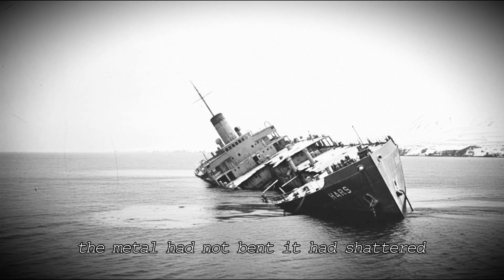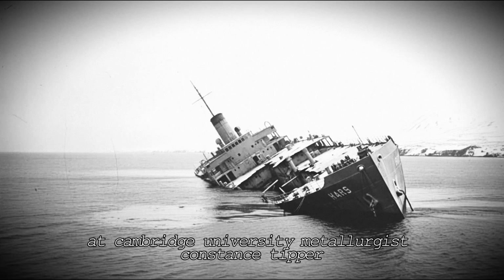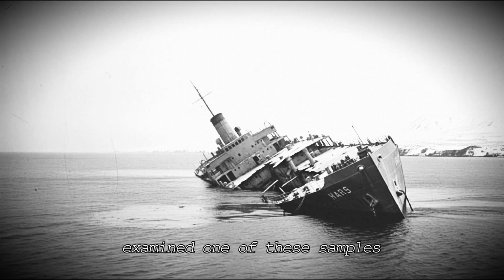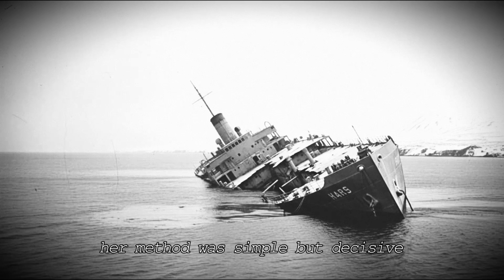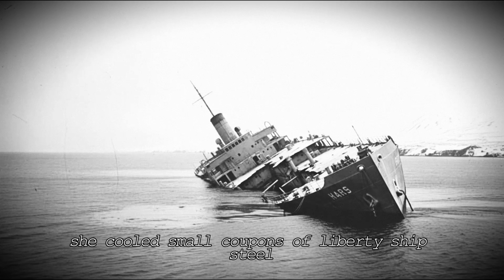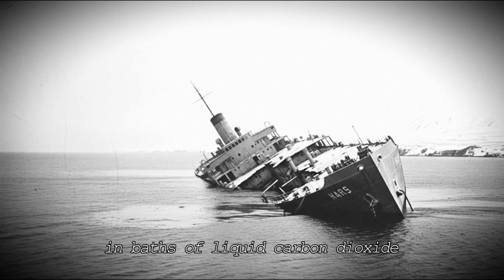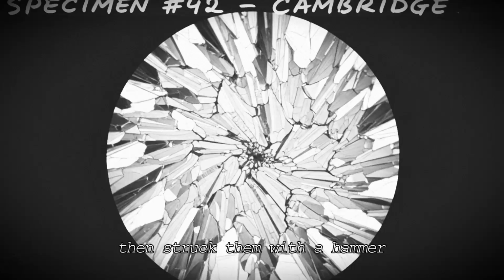It had shattered. At Cambridge University, metallurgist Constance Tipper examined one of these samples under controlled tests. Her method was simple but decisive. She cooled small coupons of Liberty ship steel in baths of liquid carbon dioxide, then struck them with a hammer in a pendulum impact machine. At room temperature, the samples bent. At freezing, they broke sharply, snapping with a clear ring.